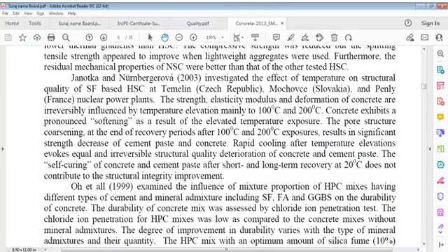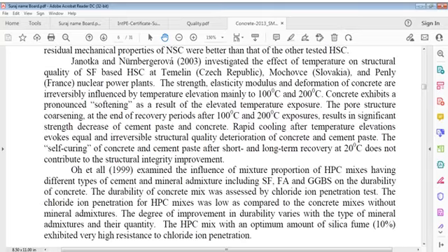Concrete exhibits a pronounced softening as a result of elevated temperature exposure. Pore structure coarsening at the end of the recovery period after 100 and 200 degrees Celsius exposures results in significant strength decrease of cement paste and concrete. Rapid cooling after temperature elevations evokes equal and irreversible structural quality deterioration of concrete and cement paste. Self-curing of concrete and cement paste after short and long-term recovery at 20 degrees Celsius does not contribute to structural integrity improvement.